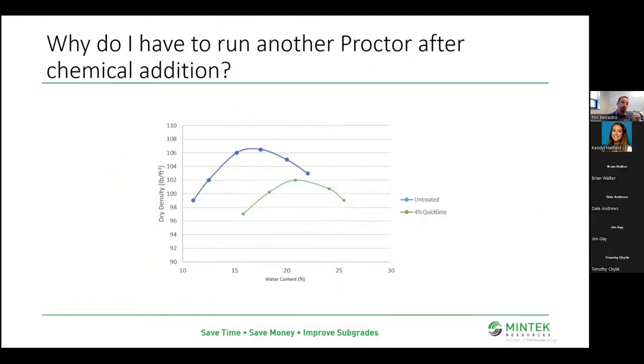Why do I have to run another proctor after chemical addition? It's important that we're hitting the right targets in the field. Remember, we are essentially making an engineered fill material as we modify that soil. You can see the untreated proctor where the OMC sits at about 15, 16, maybe 17 here. Whereas after we've treated with our quick lime, we've shifted that curve to the right, so we're able to accommodate more moisture at compaction. So it might look drier, but it's actually wetter. We can get to our OMC quicker without having to dry back as much.